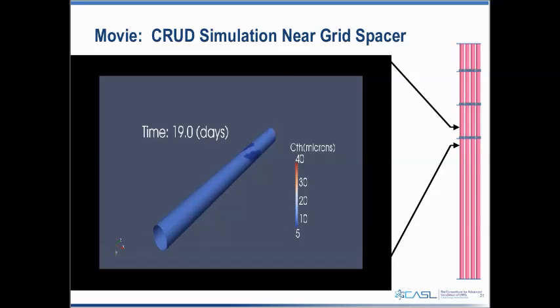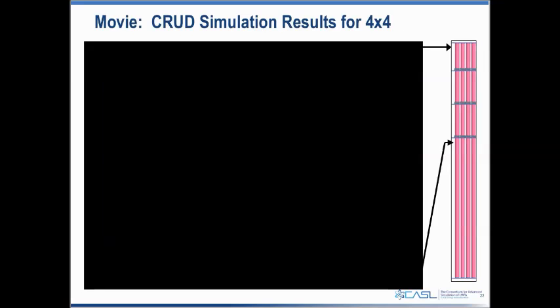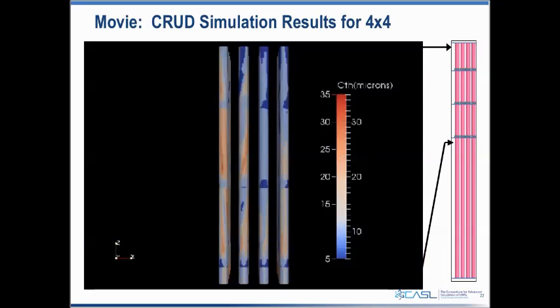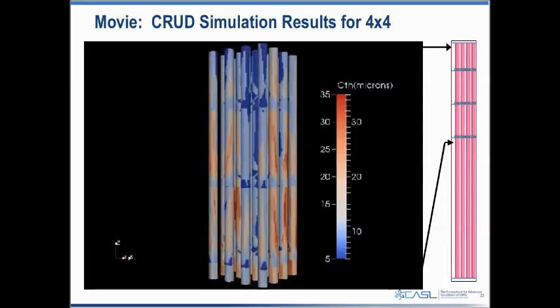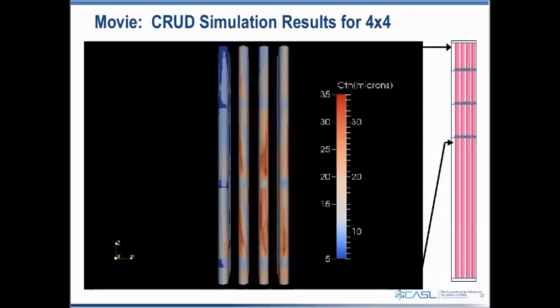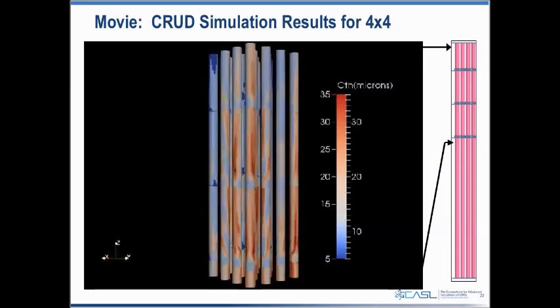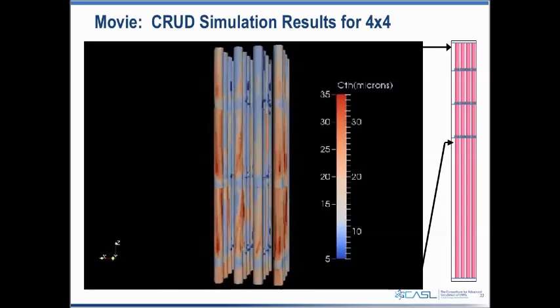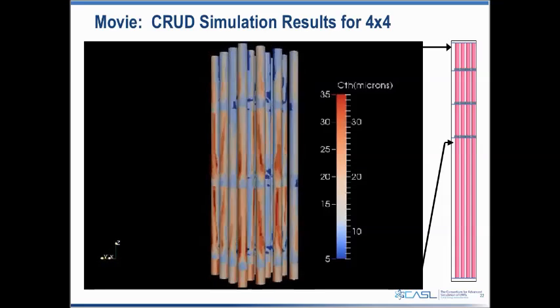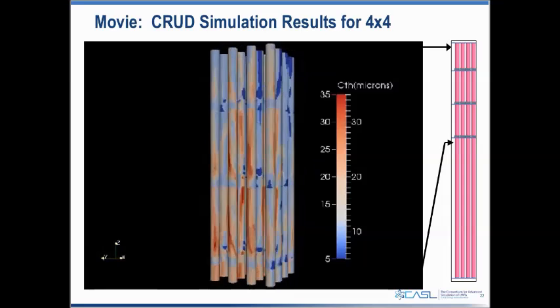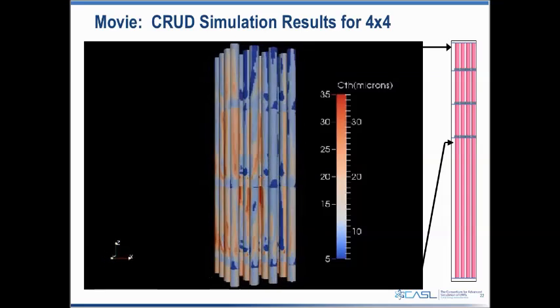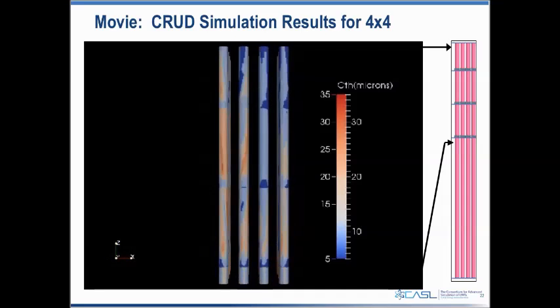One of the models we set up was in Seabrook Cycle 5, where they experienced both crud-induced power shift and crud-induced localized corrosion. So we did some modeling for that on one of the assemblies that did have both the fuel failures and the boron deposition. At the time, we didn't model the full assembly, we just modeled a 4x4 rod array.